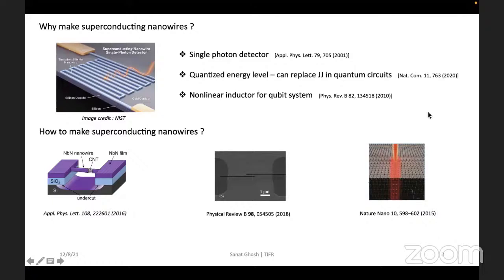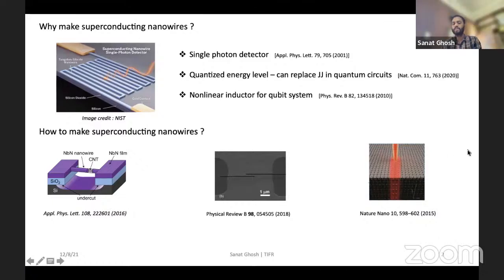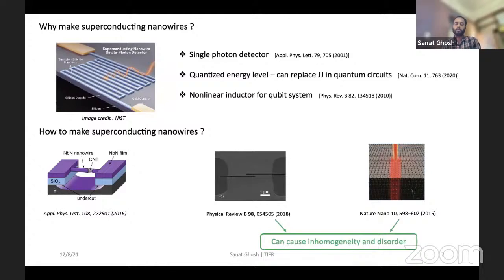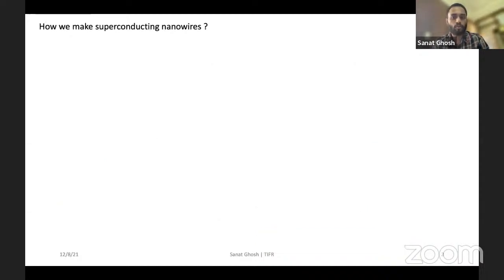Yes. Yeah. So in some cases, it has also been shown that when a high energetic ion beam is irradiated on the surface of a planar superconductor, this can also locally destroy its superconductivity, and this could be another possible way to make superconducting nanowires. Now, when we want to make superconducting nanowires from a planar structure by this method, difficulties can arise. For example, this procedure of physical etching or ion irradiation can cause inhomogeneity and disorder in the system. Now, to circumvent this issue, we have figured out a way to make superconducting nanowires in a different way.